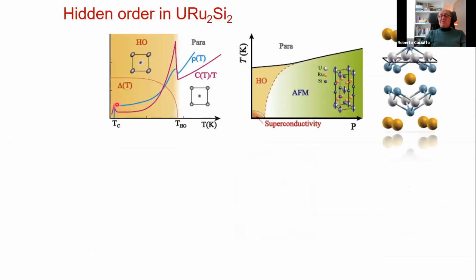The technique has been used also to try to observe the hidden order in uranium ruthenium 2 silicon 2. In this case, a phase transition is observed at 17 Kelvin. The anomalies in the heat capacity, in the resistivity, in the magnetic susceptibility are very large and cannot be explained by the presence of an ordered magnetic moment along the z-axis shown by neutron diffraction, which is of only 0.03 Bohr magneton, too small to explain the change in entropy, for instance, at this transition.